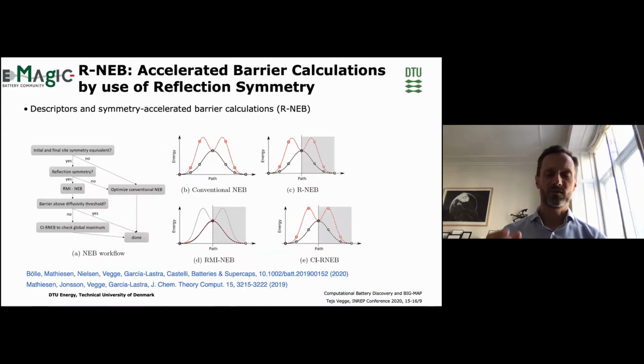An important part in computational screening for kinetic properties is that it is very slow. Calculating transition state energies is typically an order of magnitude slower than just individual structural relaxations. So we developed a methodology that allows us to accelerate the kinetic assessment. And this is called reflective NEB. It takes into account the reflection symmetries in the system.